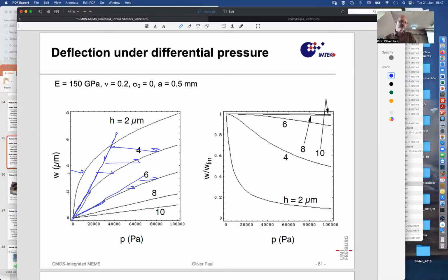And then this is shown here, and here I just drew how linear the response is, how W divided by the linear part of the deflection is, and then for the thicker ones, we see that this ratio is 1, for 10 and 8 micron thick. For 6, it already becomes 90% at 1 bar. So 6 micron is 10% wrong in deflection under 1 bar for silicon material. So, silicon 150 gigapascal is quite representative of silicon, and Poisson's ratio is also reasonable. And we're assuming no pre-stress of the membrane and a typical membrane dimension of 0.5 millimeter.